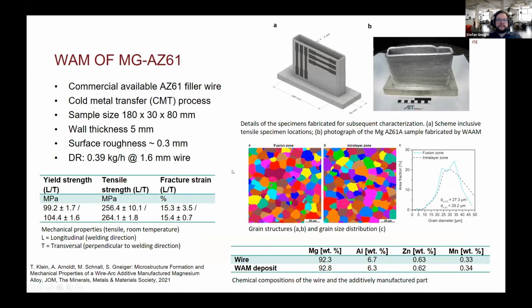For understanding the process and the material behavior, we started with commercially available filler wires, in this case AZ61 alloy, and we processed it via the cold metal transfer process you have already seen. And samples, which you can see here, with a dimension of 180 times 30 times 80 millimeters were produced for obtaining specimens, and the wall thickness was 5 millimeters. In this case, using this 1.6 millimeter wire, we had a surface roughness of about 0.3 millimeters.